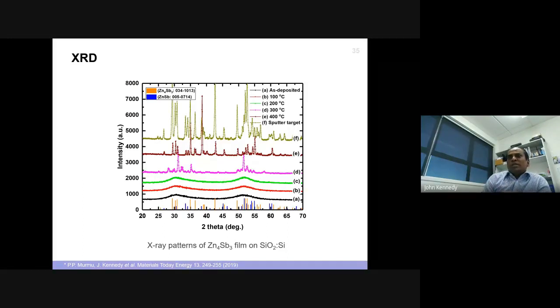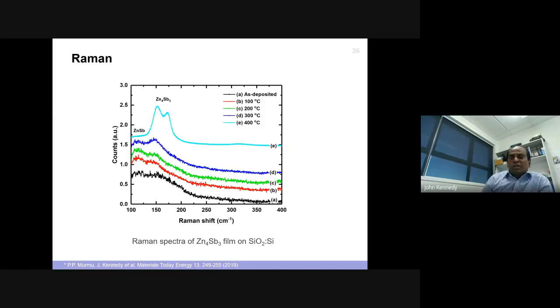If you look at the detail of this spectra, you can see we are able to manipulate the phases differently by annealing in an argon atmosphere, argon environment, basically. So this is the reason why we did zinc antimony.